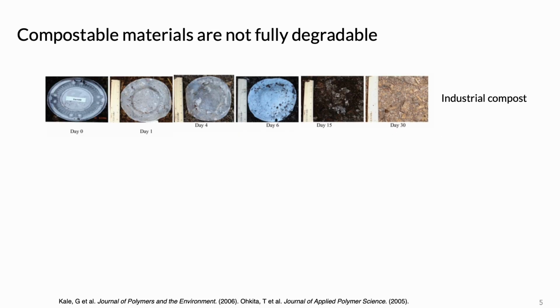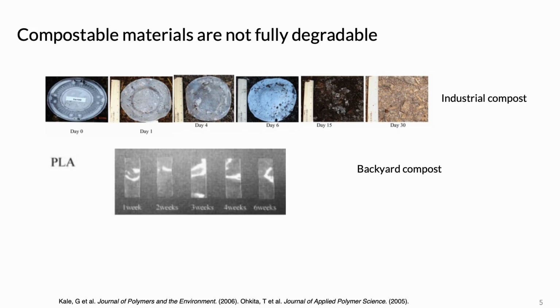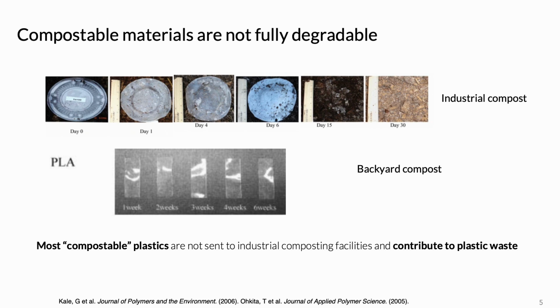Another avenue of growth in combating plastic pollution has been in the making of biodegradable or compostable plastics to replace petroleum-derived plastics, such as polyethylene, polypropylene, or PET. Polylactic acid, or PLA, is one of the most popular compostable plastics on the market because it was shown to completely degrade. But the caveat is that this complete degradation can only happen in industrial composting conditions. If PLA is left in an average person's backyard compost, the PLA retains its shape and undergoes almost no degradation up to 6 weeks. Considering that not many compostable plastics are sent to industrial composting facilities, they essentially end up contributing to plastic waste in landfills or oceans.